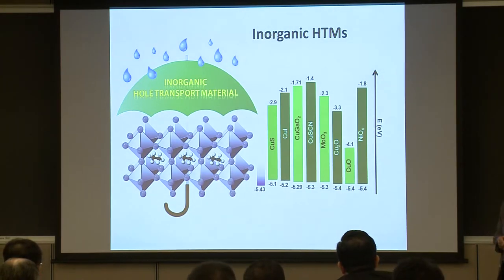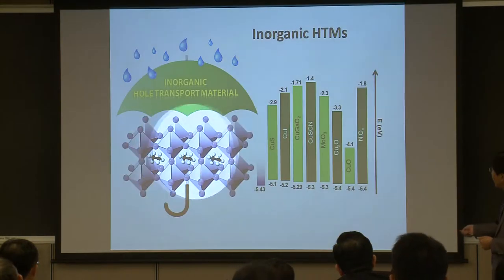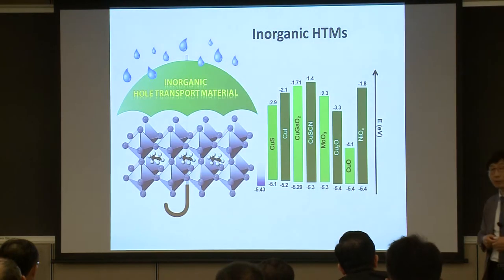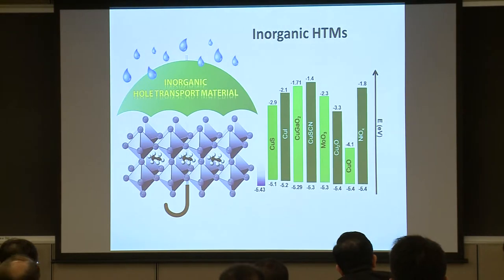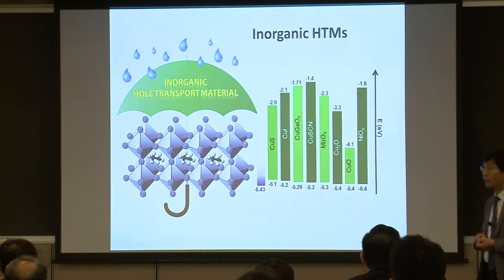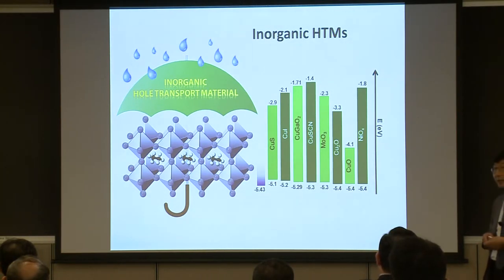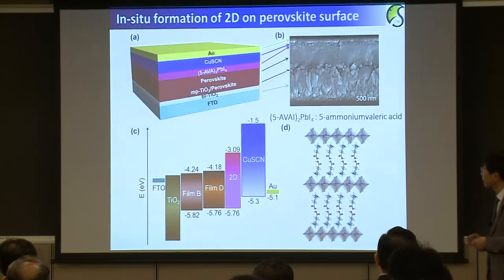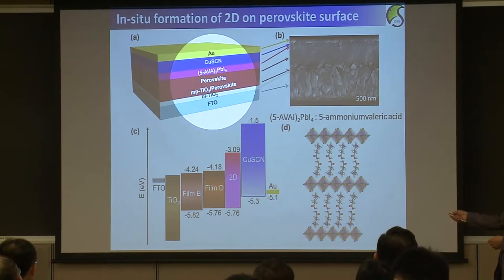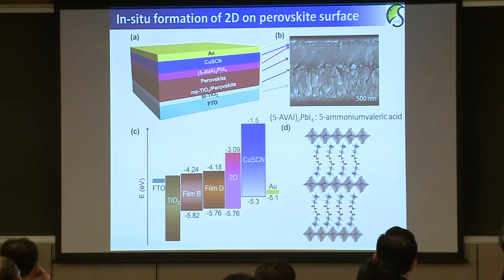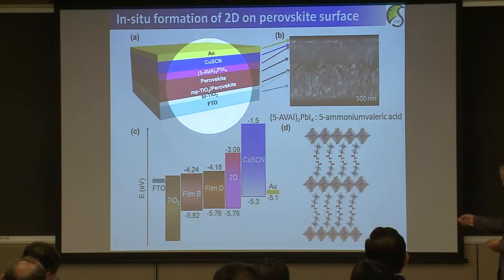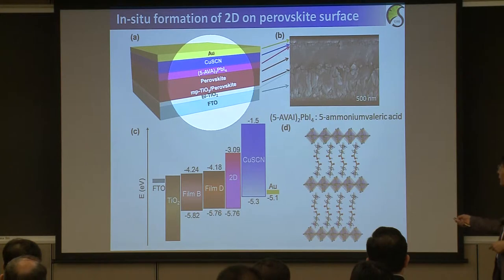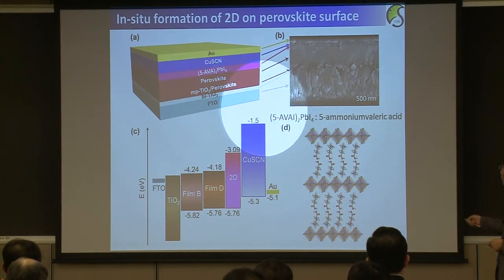And besides the organic hole transporting material, inorganic HTM was also proposed to improve the stability. So there are so many candidates here. Among them, copper thiocyanate was proposed in terms of the high efficiency also. Recently, Professor Michael Gratzel reported about 20% efficiency using the copper thiocyanate, and some interfacial engineering improved the stability. So we also use the copper thiocyanate, but it tends to react with the perovskite to form copper iodide. So you need some interface in order not to form this copper iodide. So we introduced some two-dimensional structure.